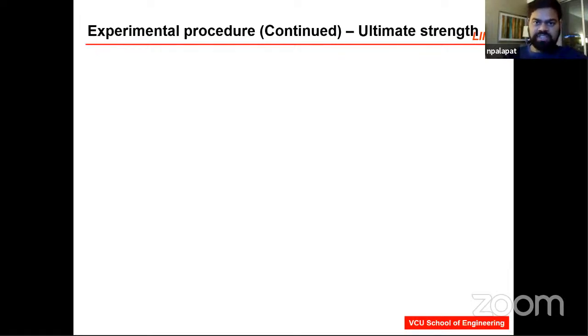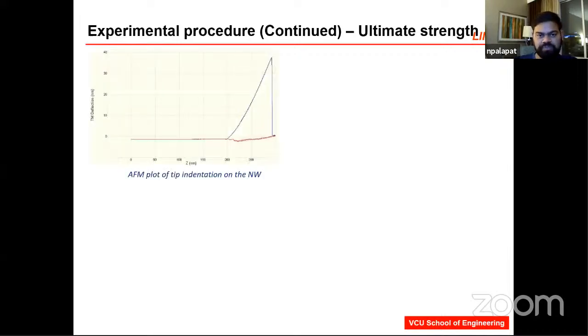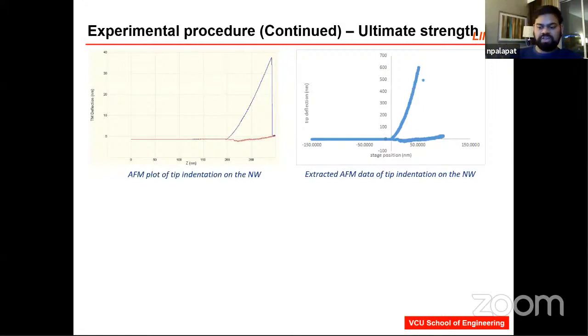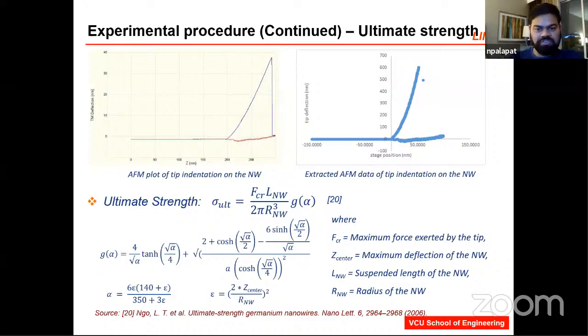So after Young's modulus, the other important mechanical parameter that we can measure is the ultimate strength. The ultimate strength is the strength that is needed to eventually break the material. So here is an example of what the approach and retract curves on the AFM look like when you break the nanowire. The tip is extending its force, and the nanowire is resisting, but at some point it breaks and the tip just retracts. So this is the significance of the curves. Depending on the data that you obtain, you can extract the information that you need from these AFM curves. So here is an equation that will give you the calculation involved in measuring the ultimate strength of a nanowire.